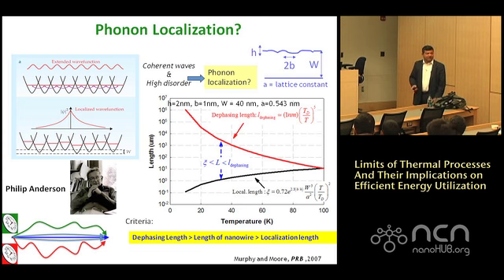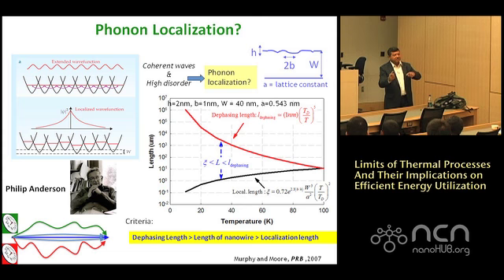One is the dephasing length. Dephasing length is the following: if you have phonon-phonon scattering, you lose all memory of the phase. And if you lose memory of the phase, these correlated scattering events are gone. There will be no correlated scattering. So the length scale of the object that you're looking at has to be lower than the dephasing length. And so that is one length scale, the length of the nanowire. The other is the localization length. That means it needs length for it to interfere, for it to localize. And there's a length scale associated with that. Well, the size of the object better be larger than the localization length, otherwise the evanescent waves will grab the energy and just move along. So that's the length scale.